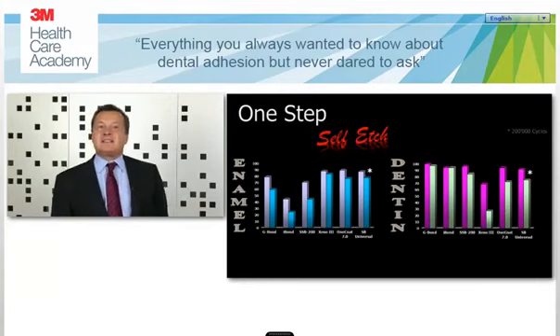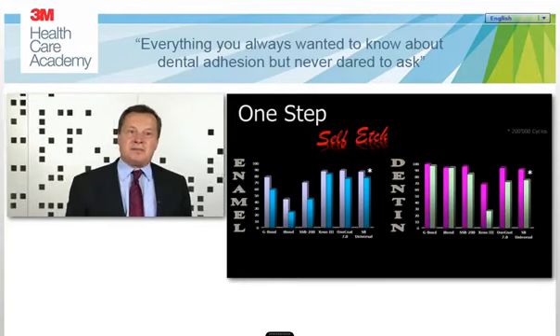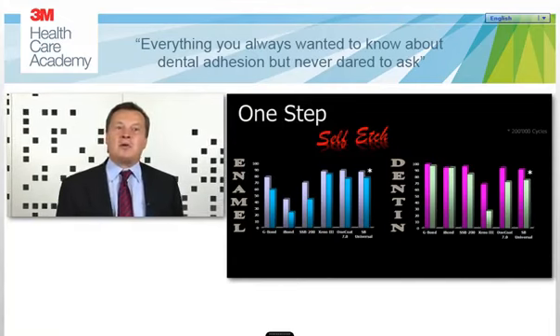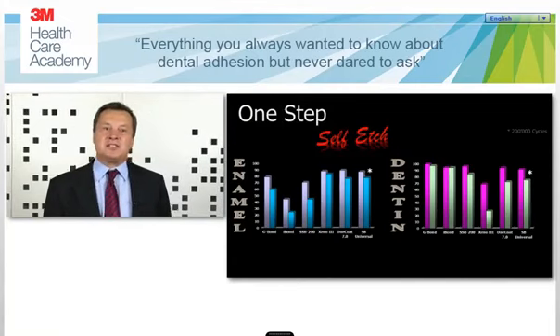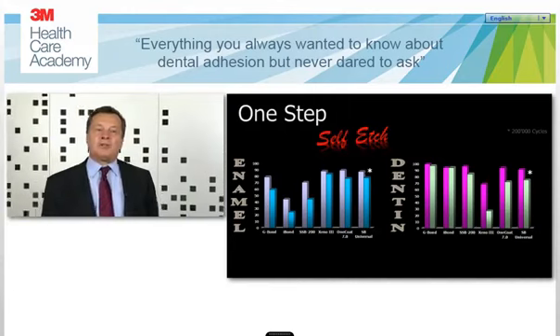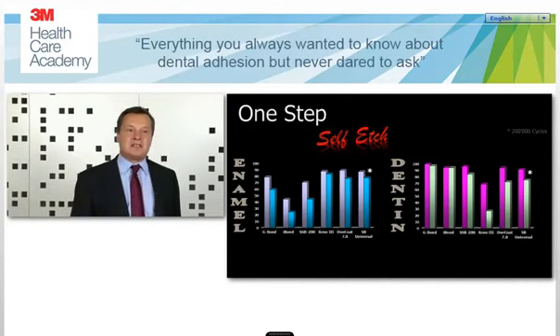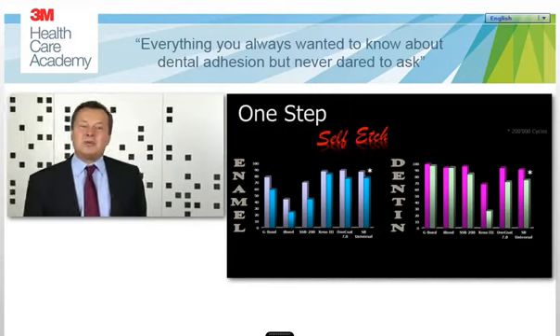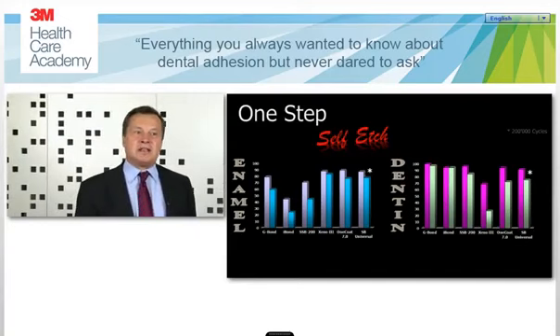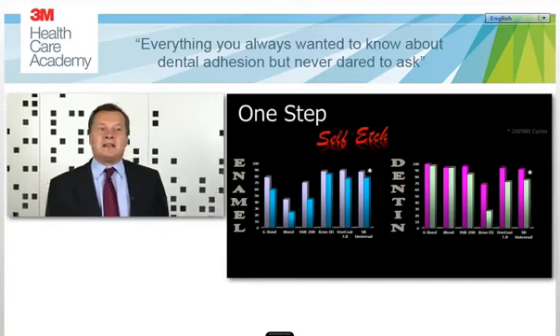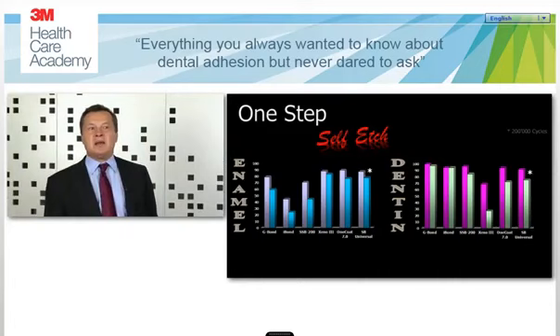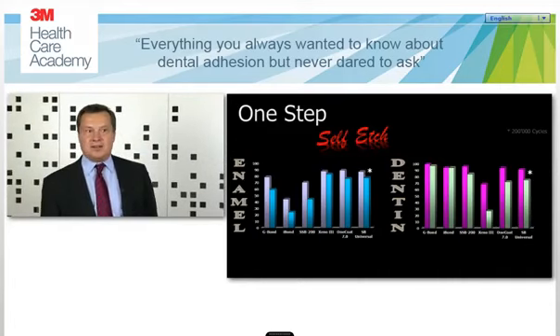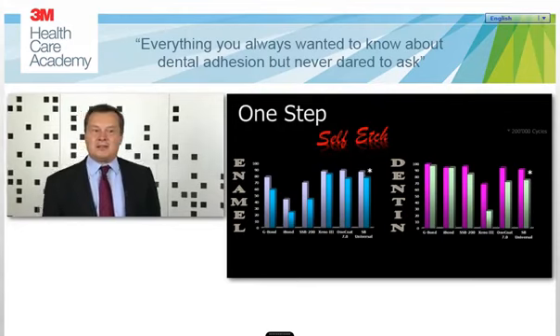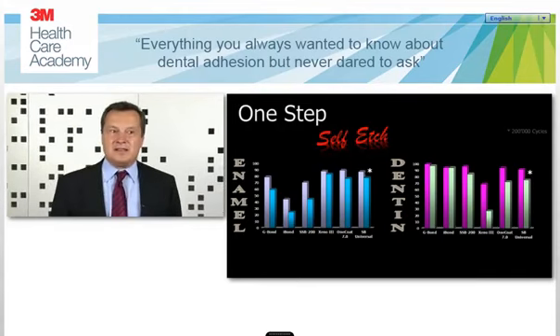But the latest developments are able to create a kind of compromise between enamel adhesion and dentin adhesion. One of the first one-component adhesive systems which was optimized in this direction was G-Bond. If you look at G-Bond, you can see that the marginal adaptation of G-Bond in enamel is almost the same as with the gold standard OptiBond FL. And on dentin, it is really outstanding.